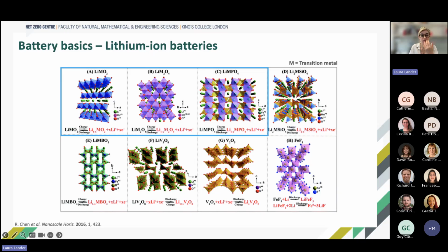They are often also called layered oxides because they have this layered structure, where you can see the transition metal oxide polyhedra connected in layers, and in between you have the lithium, which then diffuses, intercalates and is extracted, as I showed you in the previous slide, depending on whether you charge or discharge. You also have spinel structures, also lithium transition metal oxides.